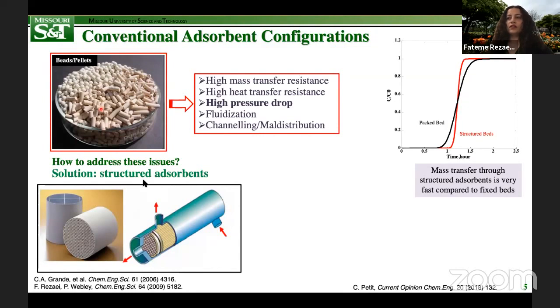But how will these contactors improve the performance? For example, we previously showed that structured adsorbents, especially in the form of monoliths, display better mass transfer characteristics compared to traditional fixed beds, as demonstrated here by displaying a sharper concentration front. The reason for that is partly because thermal effects typically associated with packed beds can be mitigated, and partly because the thin porous walls of structured adsorbents allow for rapid mass transfer equilibration, thereby allowing for more rapid cycles, and as a result, the volume of the device could be significantly reduced. The same story holds for heat transfer and thermal management.